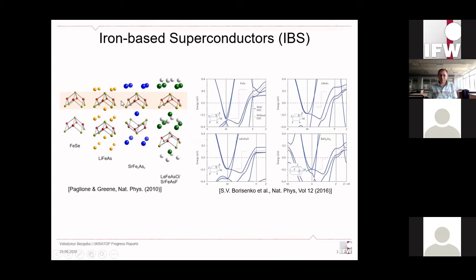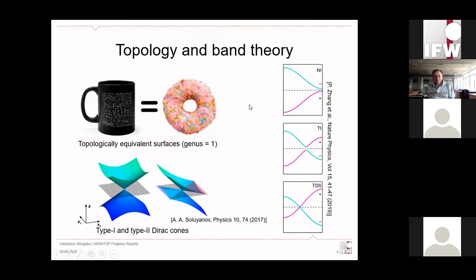You can see several different typical families of these compounds on the left and their calculated band structure on the right. As you can see, the band structure appears to be very complicated, and you can see many bands crossing the Fermi level. It turns out that this becomes a very good playground for topology, because what is topology?